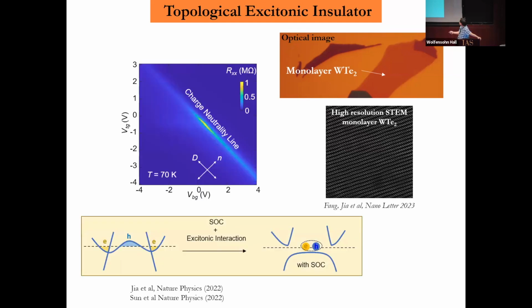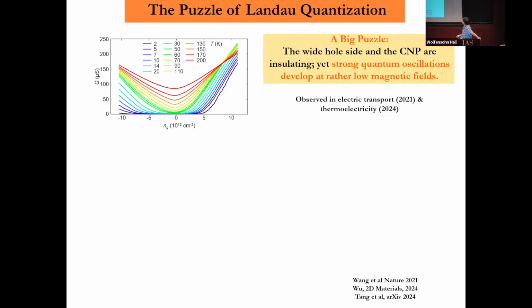If we look at the resistance map as a function of top gate and bottom gate in a typical two-dimensional device, we have two gates to control the density - you're already very familiar with this from previous talks. The charge neutrality line here shows very strong insulating behavior. What happens is that this band structure, because of both strong spin-orbit coupling and excitonic pairing, ends up giving you the insulating state here.